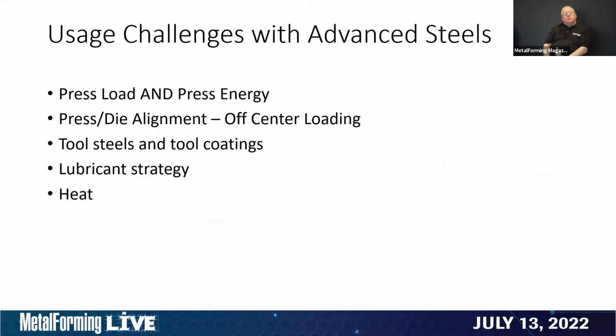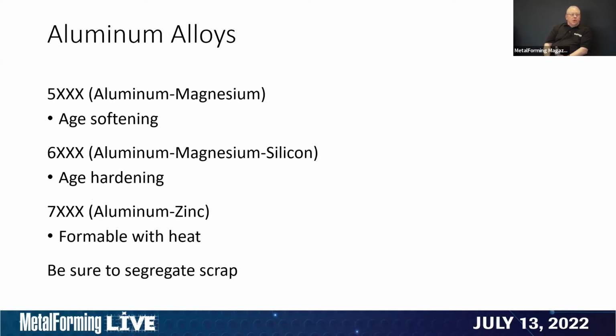So with advanced high strength steel, some of the challenges that you undoubtedly are facing are press load and press energy issues, the alignment of your tooling, tool steels and coatings, lubricant strategy, and of course, heat buildup. We're going to be discussing some of these things in our roundtable, but the bulk of these issues comes down to 2 things. One is that we're working with steels of substantially higher strength than what we were using 10 to 15 years ago. The other issue has to do with the microstructure that is unique to each specific steel grade.